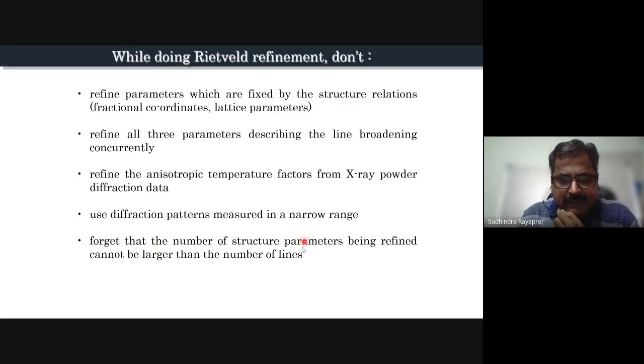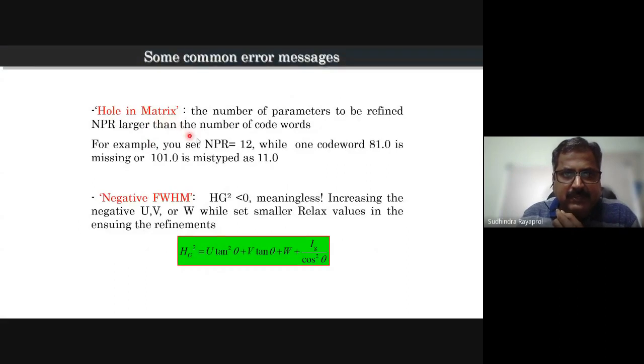And you should not forget the number of structure parameters being refined, because it cannot be more than the number of lines. So there are certain errors which come depending on how many parameters you have asked the program to refine. It can give you certain errors like a hole in the matrix. You have to check what parameters are to be refined, and whether you have forgotten defining any parameter. Like that, Fullprof is very sensitive to format. If you look at the PCR file in a text editor, you see that it is in a certain format, and any mistyping or additional space or additional character at an undesirable place, this program will start crying. It will not go further. So you have to be very careful with the format also.